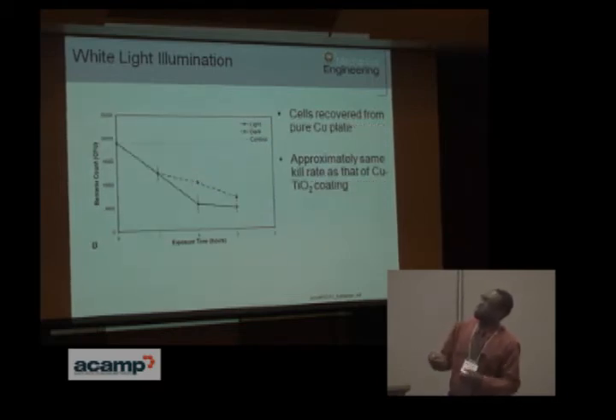Just to be a little bit more thorough, we did look at cells recovered from a pure copper plate whenever we put our samples on that. And as you can see, again, significant decrease in our number of cells as a result of exposure to white light, but also mainly because copper does have antibacterial effects itself. Now, I should point out very quickly that in this case, this is a pure copper surface here, which may tend to be more expensive than depositing a 300 micron thick coating. We're seeing some very interesting effects here.